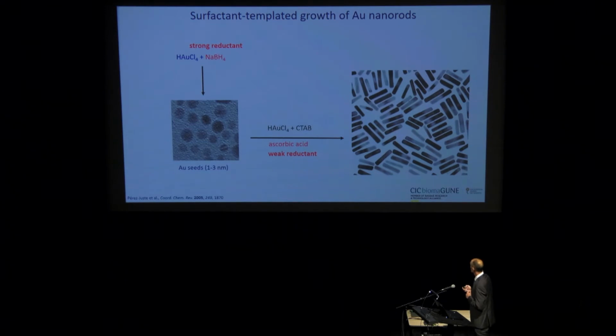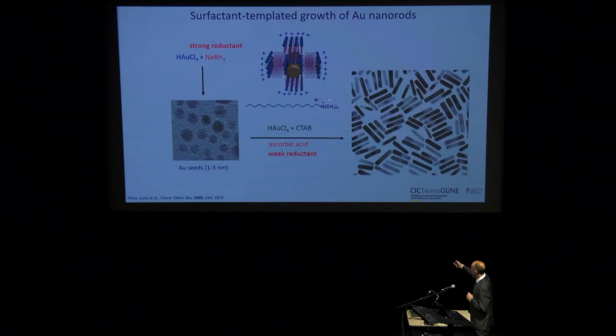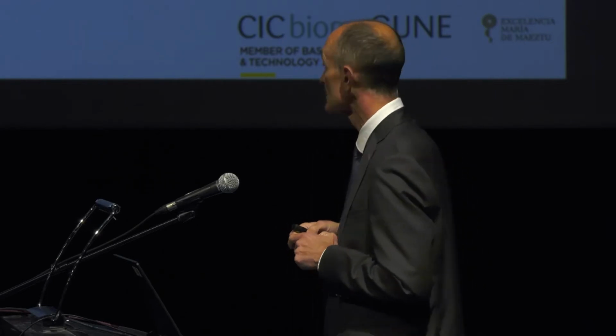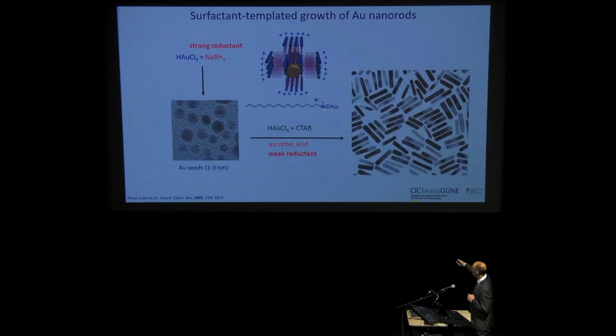Now, another important point is we are using here this cationic surfactant, CTAB, cetyl trimethyl ammonium bromide, where you have a charged ammonium head group, which will likely bind to the surface of the metal and complex with the metal atoms on the surface. And then it has a long hydrophobic chain.